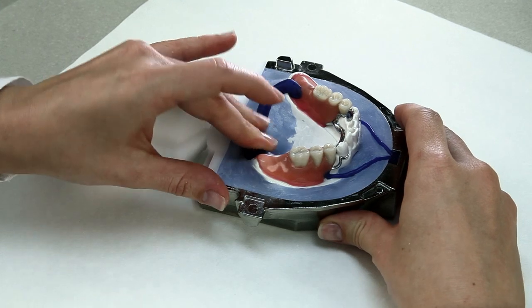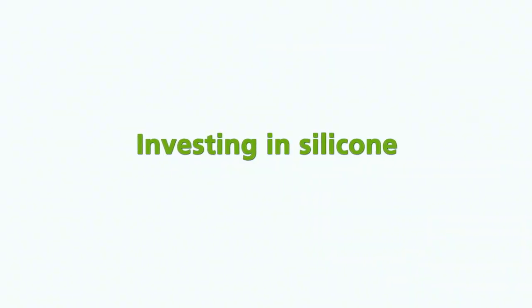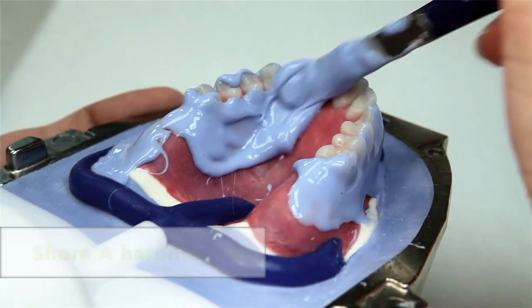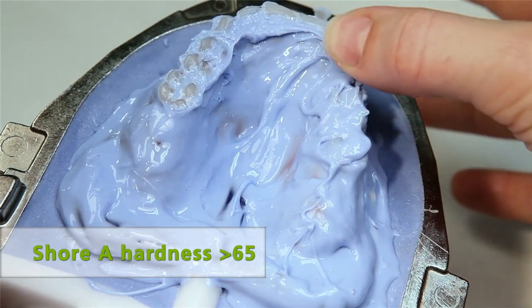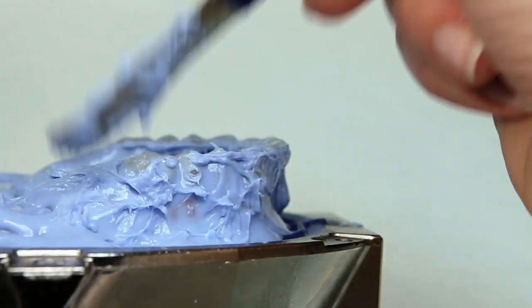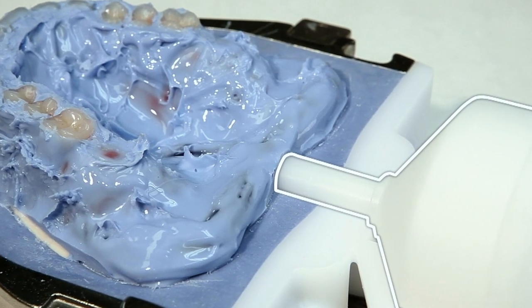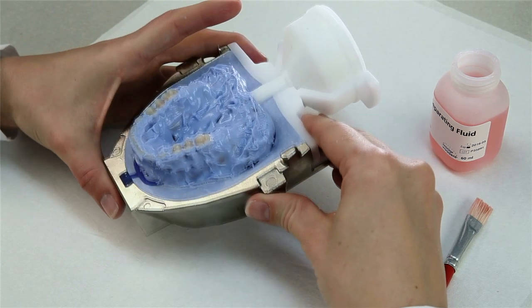The denture saddles of partial dentures are provided with a sprue each at the dorsal ends. Cover the teeth as well as the anatomically contoured alveolar area and the lingual of the palatal areas if required with a flowable to medium viscosity addition cross-linking silicone. The Shore A hardness should be at least 65. Apply retentive patterns in the surface of the silicone before it sets to secure the silicone in the stone of the counter model. Make sure that the occlusal surfaces and incisal edges of the teeth remain free of silicone. Furthermore, the access former must not be covered in silicone. After injection, silicone investment protects the teeth during divesting and saves much time during finishing.